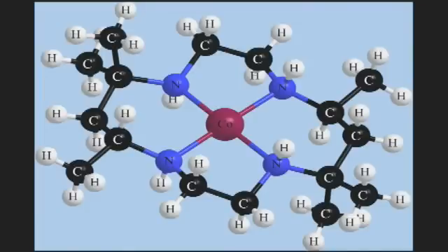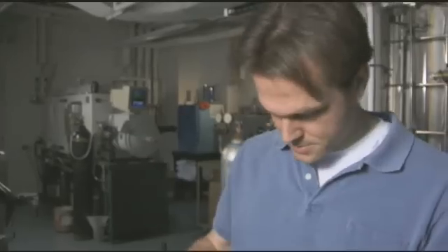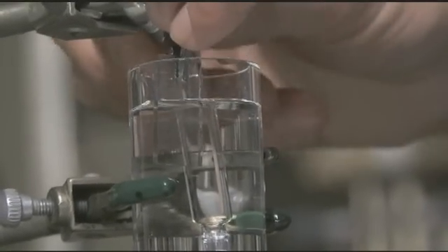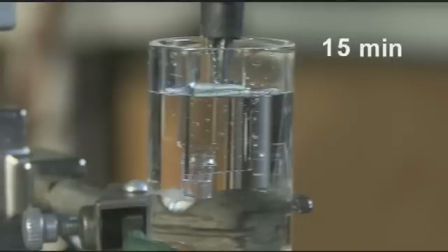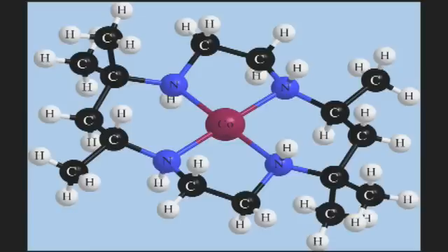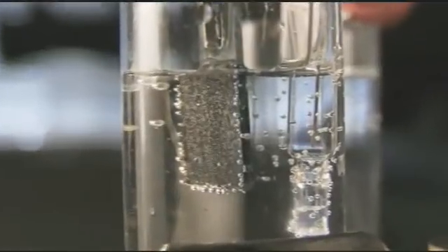This would be his catalyst. To soak up acids formed during the reaction, he added a buffer of phosphate — a common compound of phosphorus and oxygen. Then he inserted his glass electrode and turned on the power, hoping his catalyst would start generating oxygen. But what he noticed over time was that the electrode acquired a thick coating, which shouldn't happen if the molecule is in solution. It initially formed a golden-green layer over 15 to 30 minutes, then became darker and darker, and after about an hour, bubbles began emanating from the surface. This was not the result Kanan had hoped for — it meant his carefully crafted cobalt compound was falling apart, his experiment apparently a failure. But there were those bubbles. Could they be oxygen? It was too tantalizing to walk away from.